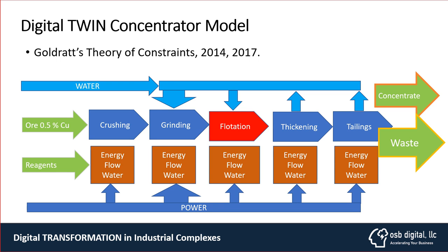And we're using the Goldratt theory of constraints to really synchronize from the material coming from the mine into the crushing, the stockpile, then we get the grinding, and then usually we see problems in flotation, but most of the time those are due to major changes in ore hardness, in the size distributions, or fines that we have because now we mine much more complicated material than we had in the past. And at the end, we can sometimes have problems in the thickening, and thickening is very important to recover as much water as possible.